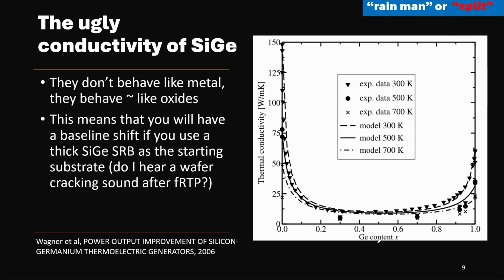It's hurting the thermal conductivity. The reason is that if you have a much larger atom dispersed uniformly across a matrix, a crystalline matrix of silicon, that creates a block for the thermal phonon. The phonon is what transports the heat. Phonon is a vibration of your ions, your silicon germanium atoms, right? The vibration of that is called phonon.